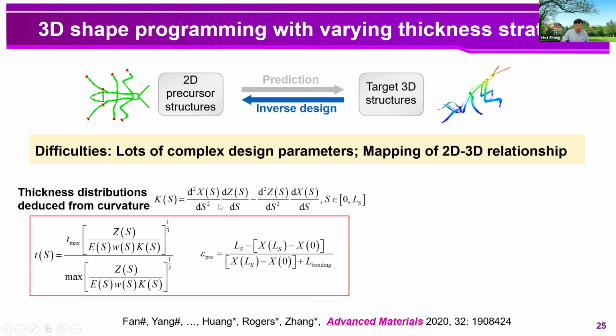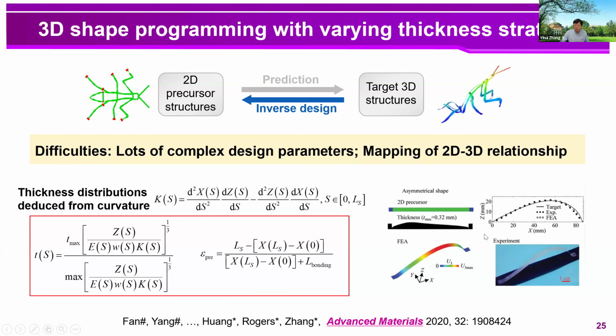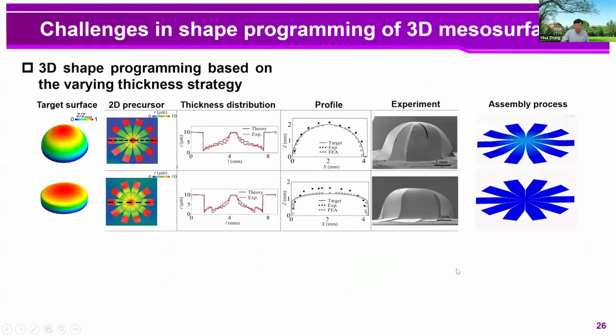And here, in terms of the thickness variation strategy, we have derived this correlation of the thickness distribution in terms of the curvature distribution for a straight beam in the simply supported condition. So according to this analytical solution, we can assemble arc-shaped or other asymmetric curved ribbons. And this model can be extended to centrally symmetric 3D surfaces. And this slide shows two examples, including a hemisphere and a drum.